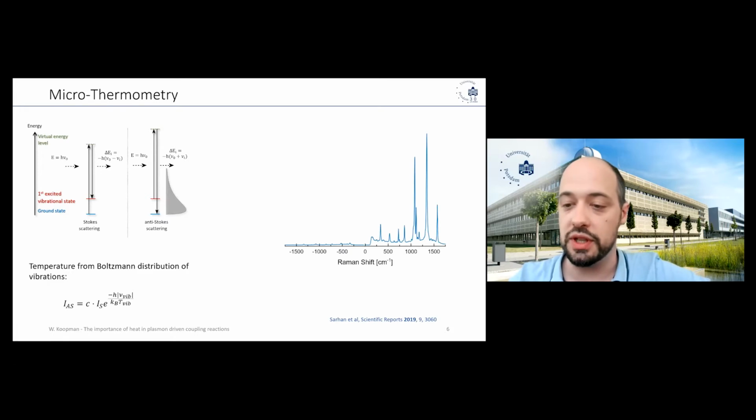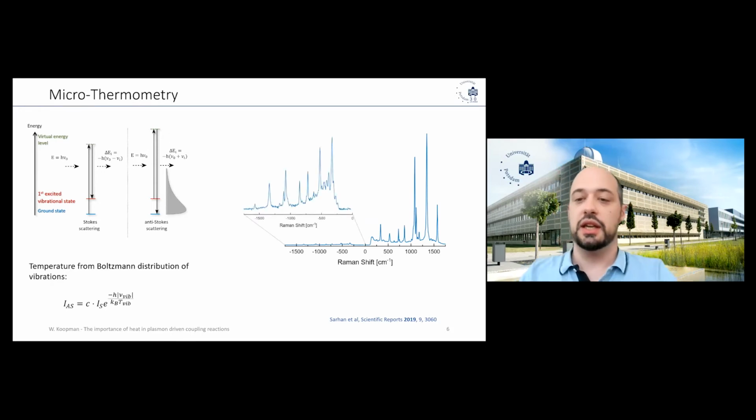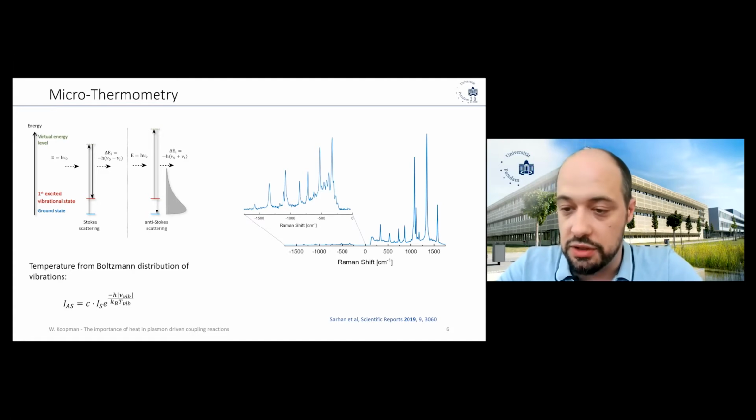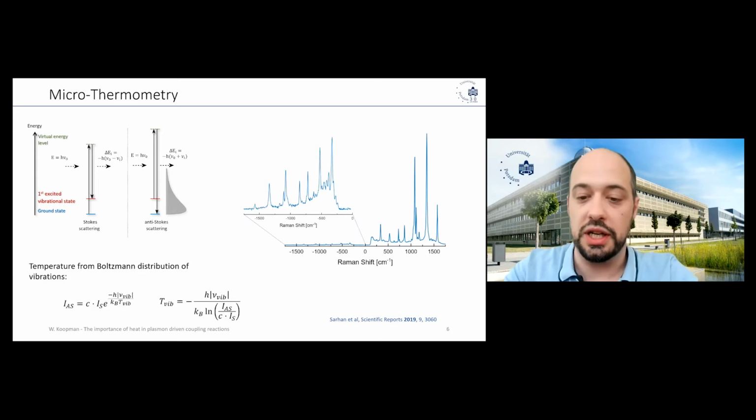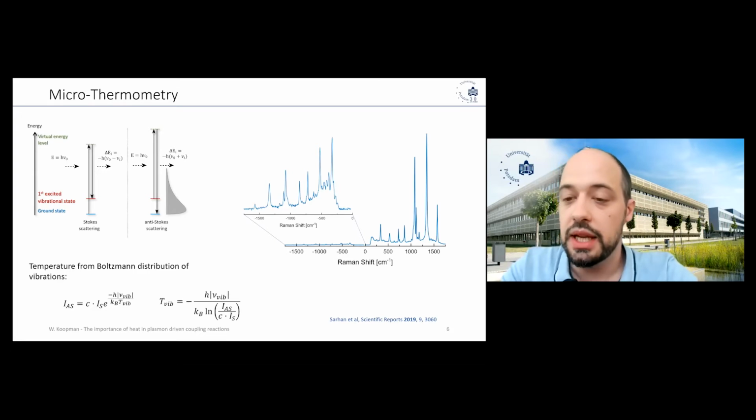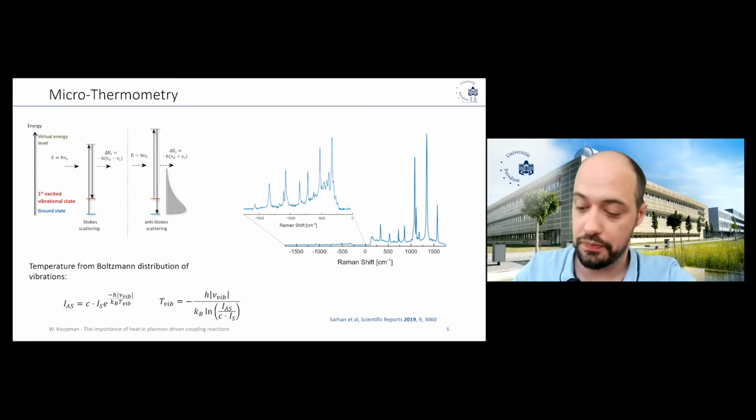We went to look if we can actually see the anti-Stokes lines, and it took us optimization, but it is possible. Yes, it's really there. Here is the magnification of the anti-Stokes line, so you can actually see it. Now, in principle, you can calculate the temperature by this formula. The only thing you have to do before is get rid of this background somehow. In the anti-Stokes case, this background is not only annoying, it can be helpful.